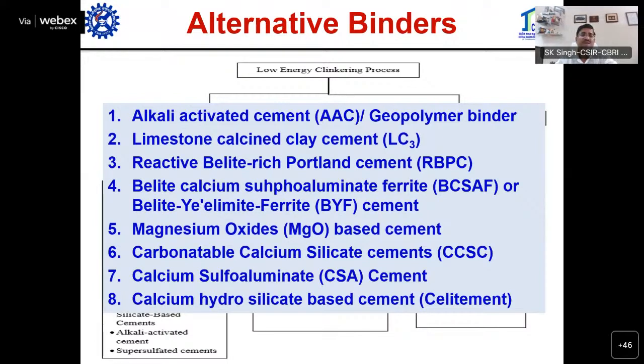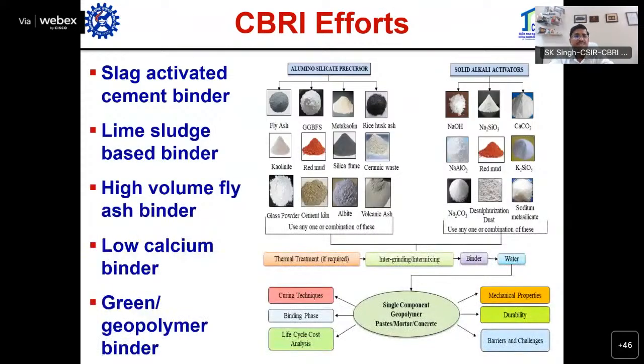It has really been a very good effort where we can say carbon reduction. Here, CBRI has made an effort on slag activated cement binder, up to 30% slag by mechanical chemical treatment, and reduced the clinker cement ratio by 35%. And we also worked on the lime sludge based binder, where this ratio has further reduced by 50%. Also high volume fly ash binder, low calcium binder, green and geopolymer, what we are working on.